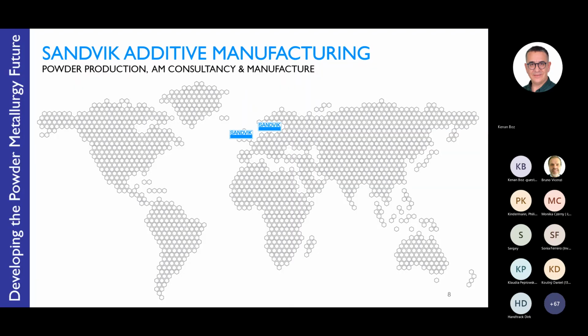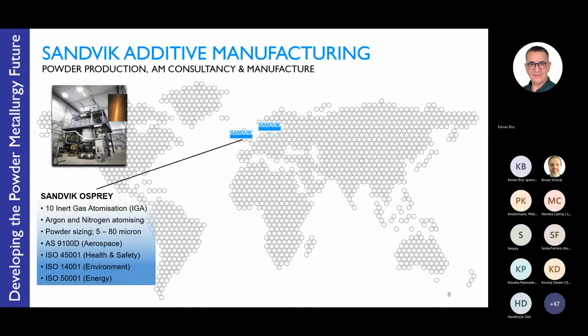Just to highlight Sandvik's facilities in this area, we have inert gas atomization in the UK, 10 inert atomizers actually, and have been producing powders at this location in South Wales, the Osprey facility, for more than 40 years, employing both argon and nitrogen atomizing. And we have a range of different size distributions, from an average size of 5 microns up to 80 microns. So therefore providing powders for different applications, aerospace approved, and have various ISO standards associated with health, safety, environment, and energy, and ultimately providing credibility when it comes to sustainability.